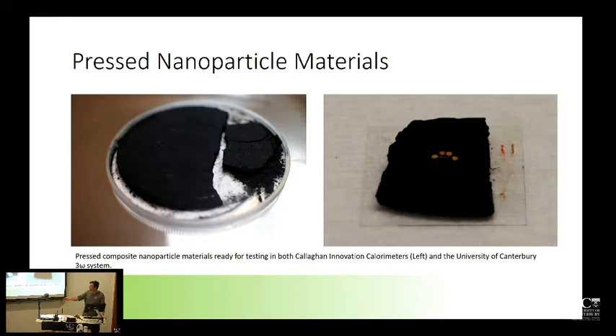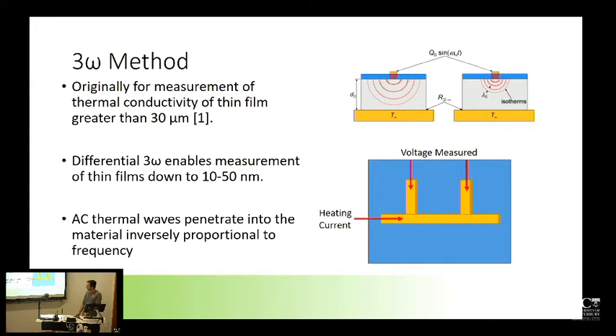So the whole idea is that you can pass an electrical current through the centre portion of this line, and then you can monitor the voltage across these 2 top points in a 4-point probe configuration. And the third harmonic of your electrical driving frequency is linearly related to the temperature of the line. So why this is advantageous is in the calorimeter you have this large heating plate, so you're measuring the temperatures through a derived mean, and then you have a heat flux sensor separated by some distance, and then everything's separated and spread out, not necessarily inexact, but just displaced from each other physically. With the 3 omega method, what you can do is fabricate this gold resistance thermometer directly and intimately in contact with the surface of your sample, and then pass an electrical current through it, which provides the heating, so the input into the system, and you can simultaneously measure what the output of the system is in terms of the temperature.